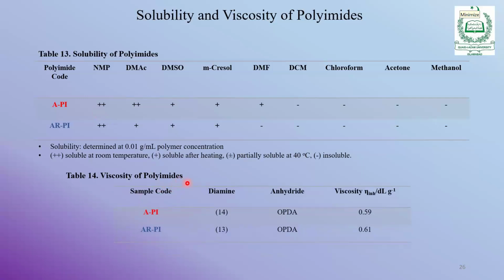Also, the viscosity of polymers is important because it gives you an insight into the molecular weight of the polymers. We used a Ubbelohde viscometer in the NMP solution, and we see that moderate viscosities are observed, which means that neither high molecular weight polymers nor very low molecular weight oligomers are there. So the polymers are formed with a medium range of molecular weight, around 40,000-50,000 grams per mole.